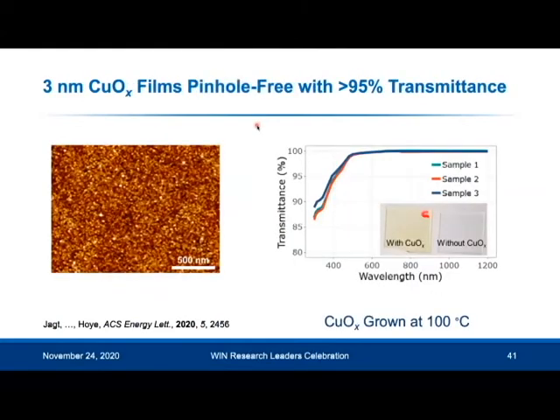One of the problems with Cu2O is that it has a narrow band gap, so it absorbs visible light. So if we have it too thick, it's going to absorb some of the light that would otherwise go to the perovskite. So we made cuprous oxide films which are only 3 nanometers thick, and we found that it was pinhole free, and because it's so thin, the transmittance was very high. It was close to 100% over the visible wavelength range.